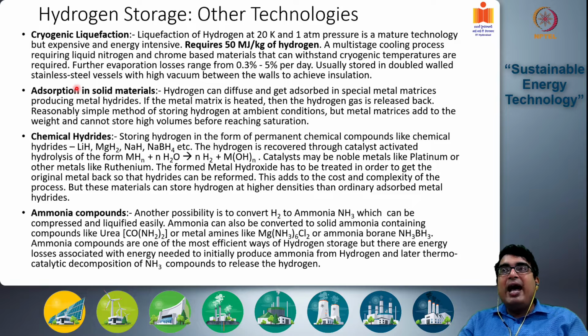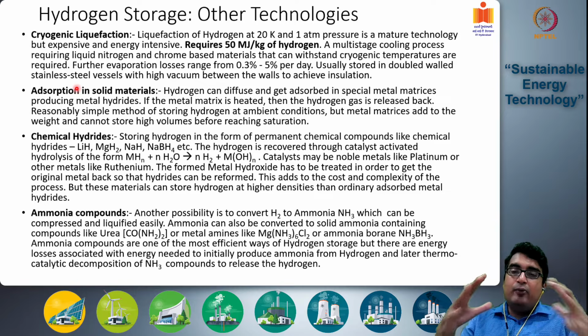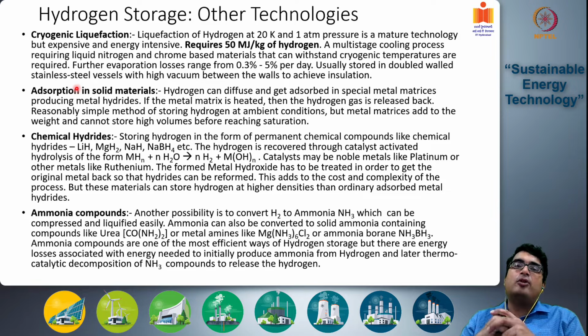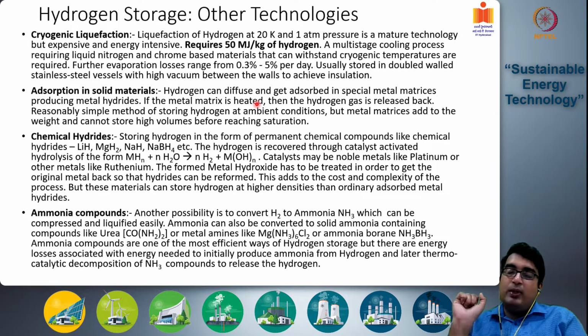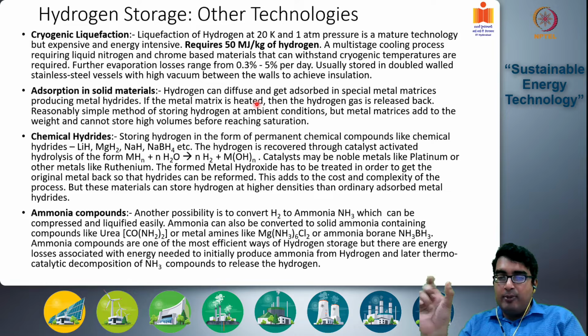Further, you will have evaporation losses of 0.3 to 5% per day. So the liquid hydrogen, even if it's stored in very well insulated containers, will still suffer from significant evaporation losses per day, which makes it not viable for long-term storage systems. Okay. These are usually stored in double-walled stainless steel vessels with high vacuum between the walls to achieve insulation. So you have double-walled vessels and there is a lot of vacuum inside the walls to remove conduction and convection losses, and radiation will be minimal because hydrogen is extremely cold. Okay.